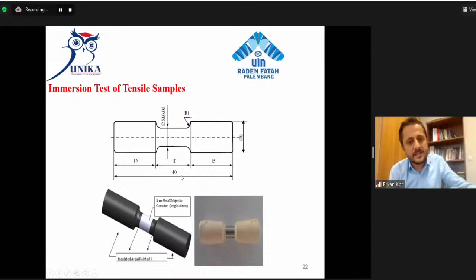A schematic of the tensile samples used is shown here for immersion of tensile samples. To avoid corrosion attack here, we insulated these areas, and the white areas are not insulated. They are exposed to simulated body fluid, and then we do tensile testing to see the mechanical strength. Okay.